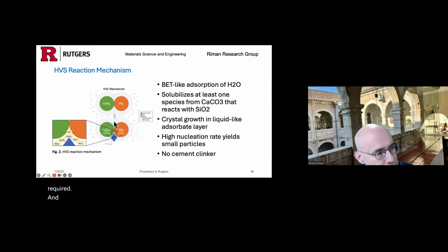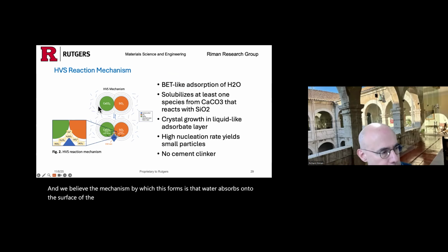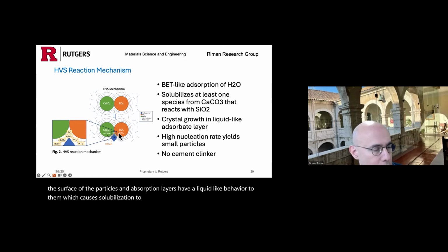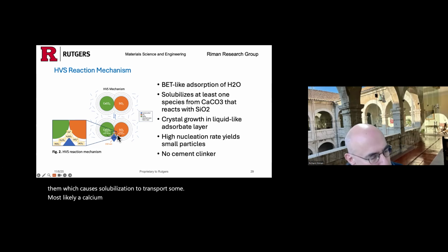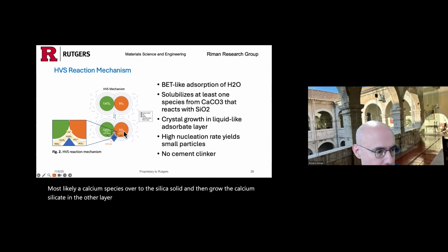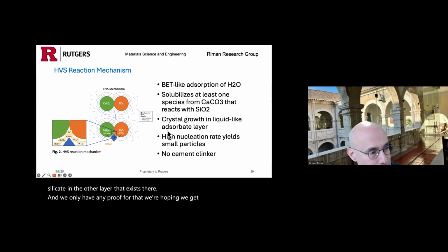And we believe the mechanism by which this forms is that water adsorbs onto the surface of the particles, and adsorption layers have a liquid-like behavior to them, which causes solubilization to transport some, most likely a calcium species, over to the silica solid, and then grow the calcium silicate in the other layer that exists there. And we don't have any proof for that. We're hoping we get some research funding so we can prove that we understand the mechanism.